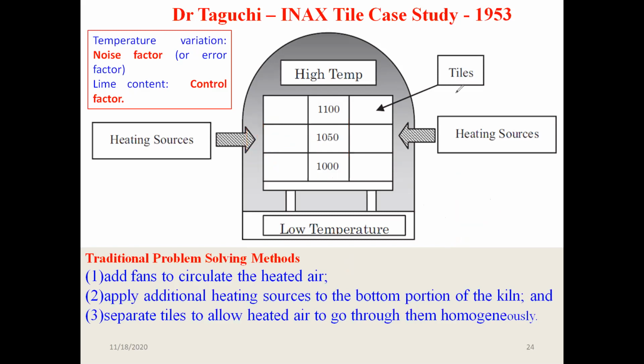Surprisingly, what happened, at 5% of the lime, this thickness variation was not there. But at the same time, when they measured, the temperature variation was there. Even after conducting all the experiments, the temperature variation did not go off, because Dr. Taguchi did not follow the traditional method. He did not put a fan. He did not put additional heating sources. He did not have chambers. He was only having the same setup. The only thing is, he was varying the chemical constituents of the tile raw material, and he measured the thickness. And surprisingly, he came to know that the variation problem had been solved.